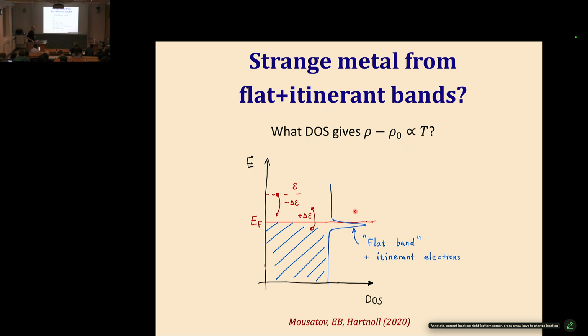But why do you see this scenario as so exotic? If I have a multi-orbital system with some strong hybridization driven by a crystal field, with energy scales of the order of kT, I will have something that looks like a flat band plus some itinerant band. So it's not so unusual to get this behavior over a range of temperatures, I think. In fact, we propose this as an explanation for the linear in T resistivity in a different ruthenate, the bilayer ruthenate, where there's a critical magnetic field where the resistivity is linear down to quite low temperature.